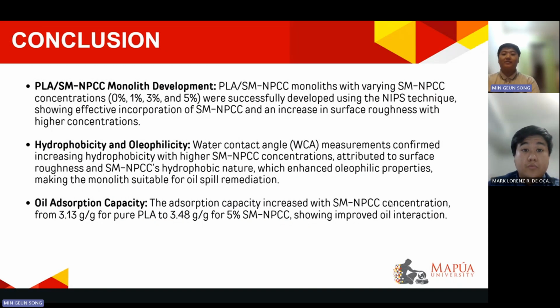To answer the specific objectives of our study, our conclusions are presented as follows. PLA SM-NPCC monoliths with varying SM-NPCC concentrations, which are 0, 1, 3, and 5%, were successfully developed using the NIPS technique, showing effective incorporation of SM-NPCC and an increase in surface roughness with higher concentrations. Water contact angle measurements confirmed increasing hydrophobicity with higher SM-NPCC concentrations, attributed to surface roughness and SM-NPCC's hydrophobic nature, which enhanced oleophilic properties, making the monolith suitable for oil spill remediation.